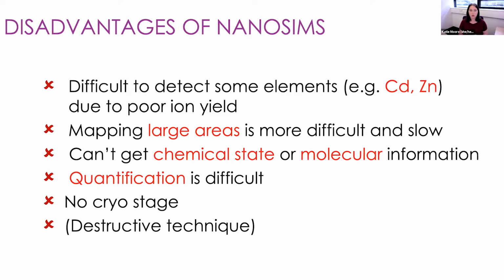Quantification is difficult. What I mean by that is it's very difficult for me to say, at a particular point on the sample surface, what is the percentage of elements that you can get from that. We can look at relative amounts, but I can't say you have 3% of your particular element in that particular location.